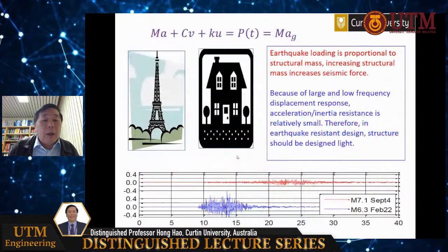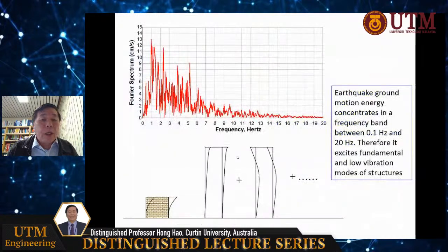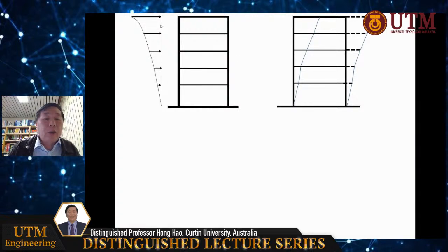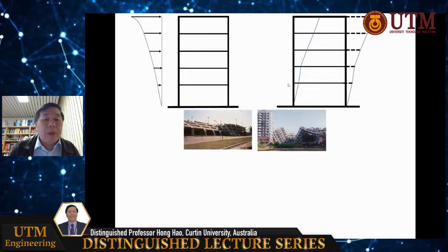But if you look at the earthquake, it's completely different. I'll speed it up. This is a typical earthquake energy or Fourier spectrum. Earthquake ground motion has most of its energy distributed in a range of say 0.1 hertz to 20 hertz. That falls into the fundamental or low vibration modes. If you have a very stiff, short structure, the first mode will be primarily excited. If you have a tall, slender, flexible structure, probably the first few modes will be excited. That is earthquake loading, and so you see the interstory drifts. That is the typical response mode of earthquake damage.